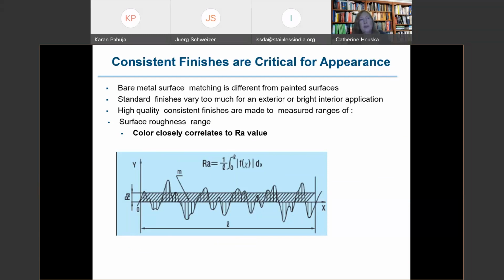One of the primary means of documenting finishes, quantifying them, is the surface roughness RA, which is an arithmetic mean average of the surface finish. I'm showing that on there. You basically take half the peak height and measure that. It is important to note that the color, or at least what we perceive as color, closely relates to the RA value, in addition to it relating to the chemistry.